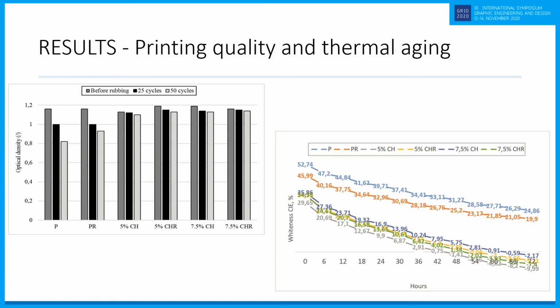The investigation of the optical properties of the obtained paper samples during accelerated thermal aging showed that the aging of the sample papers with the addition of chitosan and chitosan and rice starch blends had the same behavior through the 72 hours of aging. The largest change was observed in the first studied parameter, whiteness, which after the end of the accelerated thermal aging decreased by approximately 50%.